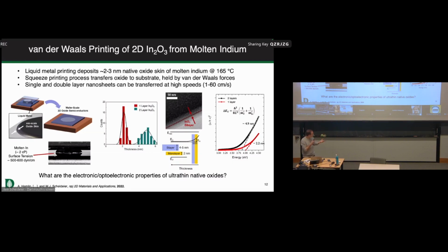So in this first round of studies, what we did is we found that if we deformed a droplet of indium, the solid oxide that grows on it would automatically get transferred to whatever surface it's being deformed across by van der Waals. And we discovered, one, that we could form single layers that are just 2 nanometers thick.